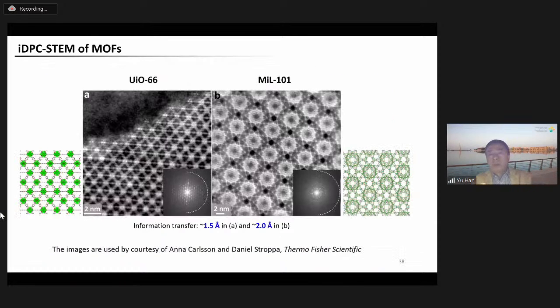Well, as I mentioned, MOFs are much more beam sensitive than zeolites. The good news is that iDPC-STEM can also be used for MOFs. Here are the iDPC-STEM images of UiO-66 and MIL-101 with a resolution of 1.5 and 2.0 angstrom respectively. And these resolutions are as good as the resolution we observed using ultra-low-dose HRTEM.